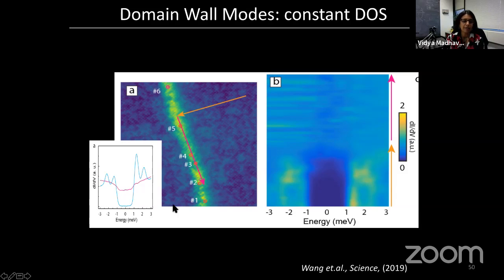So zero density of states is this dark region here. These coherence peaks would be these yellow lines here. And then this is following this and then following the red arrow. As you go along the domain wall, you can see that inside the gap, you see a very flat density of states. So there are no sharp features or no peaks, just this flat density of states. So constant density of states is what we see on the domain wall.